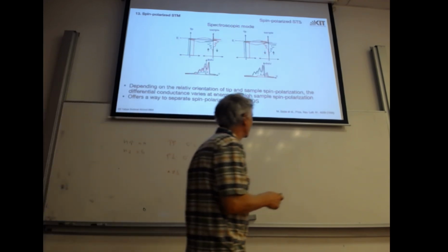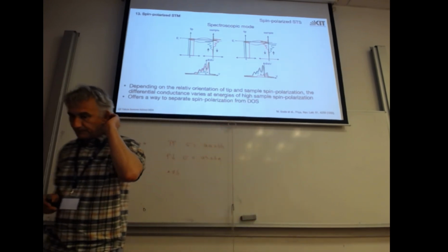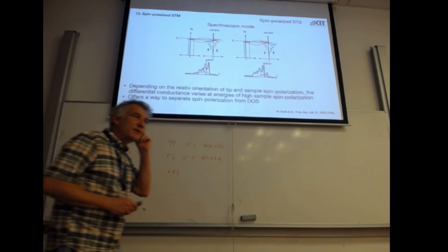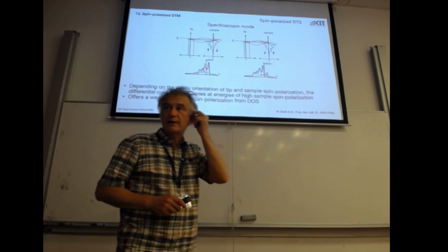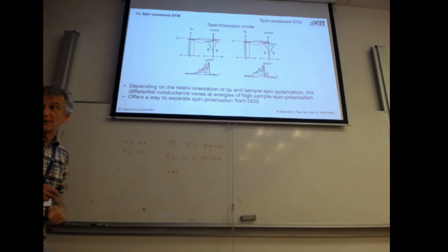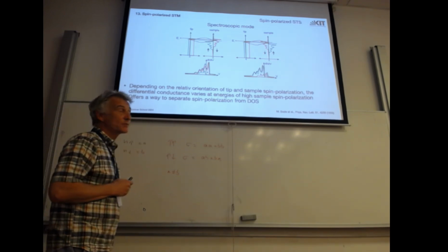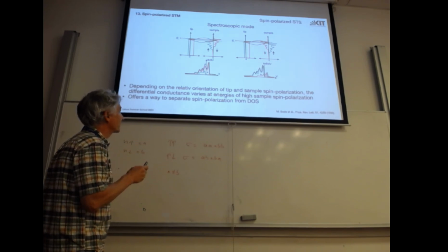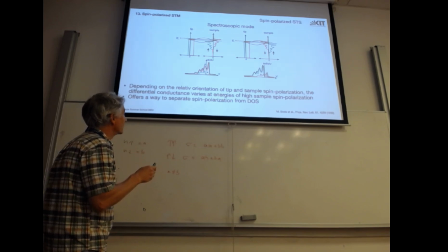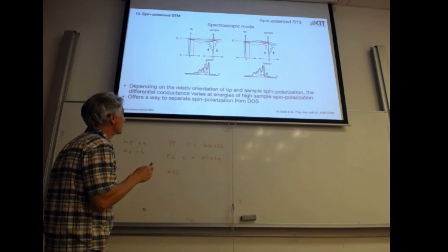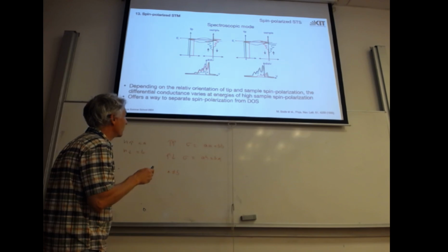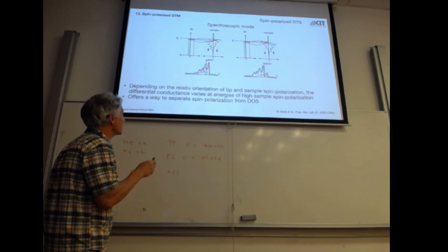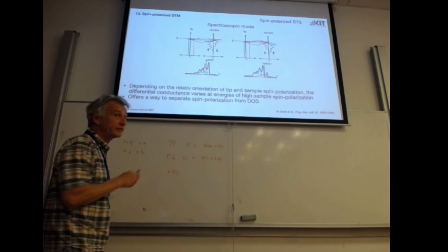until 1998, when Matthias Bode had a very nice idea. So we want to separate spin and density. So why not do tunneling spectroscopy now with the spin polarized tip? And we go to the Tersoff-Hamann model, constant density of states in the tip, but spin polarized. So we have minority and majority in different densities of states. Our sample is also spin polarized. So again, we tunnel from green to green and red to red. So I have to take this red curve and this green curve, add them up and weight them by this density of states. So the green curve has small intensity, the red curve has large intensity, larger than the green curve.